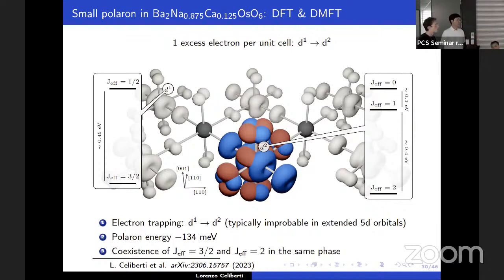In the manganite case, the Jahn-Teller distortions are coupled to each other. What about in this system? Do you think of the collective, so cooperative Jahn-Teller, or not? Two points regarding it. In the pristine material, without the polaron, you have some form of cooperative Jahn-Teller, which is coupled to the canted ordering, because you have this orthorhombic distortion, which has one direction on one plane and another direction on the other plane, like the magnetic moments. And there, that distortion is coupled. But the diagonal distortion of the polaron is not coupled. This is an impurity. It's like a Jahn-Teller impurity.